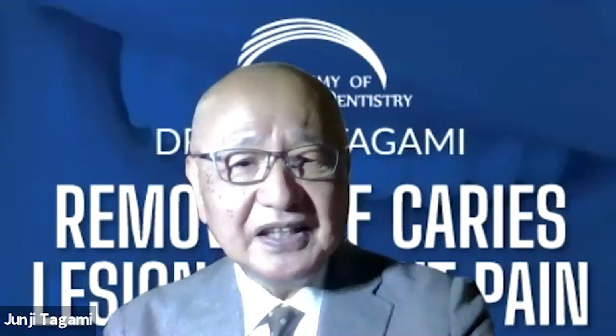Then at that time, through the thin layer of the flowable composite, the light is applied to the bonding layer again. That kind of indirect irradiation is also very effective to increase the bonding to the tooth surface. Then we can create a very reliable bond. So that's why it's better to think that the flowable lining should be involved as a bonding procedure. Then you can move on to your favorite filling technique immediately after that.